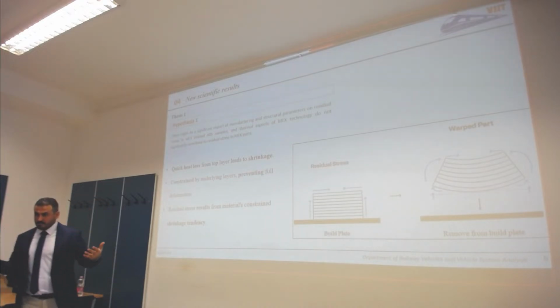But at the beginning, it's about the residual stress. As we know, it happens due to the quick heating and cooling of the parts. So when the top layer is deposited, it tries to shrink, but it's constrained by the underlying layers. This tendency to shrink and the constraints result in the residual stress. I made 3 different studies for the first thesis point.